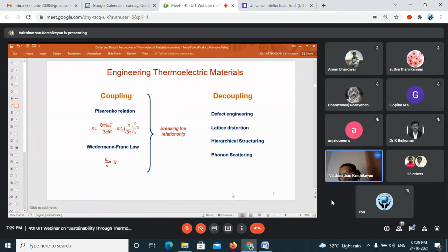So we have tried a novel technique, introducing defects into the material. For example, silicon wafers do not have high electrical conductivity. To make them highly conducting, we introduce phosphorus atoms into the lattice to achieve n-type nature in the material. In the other case, we dope with boron to achieve p-type characteristic. Phosphorus is for n-type and boron is for p-type. That is the doping process to enhance the electrical conductivity.